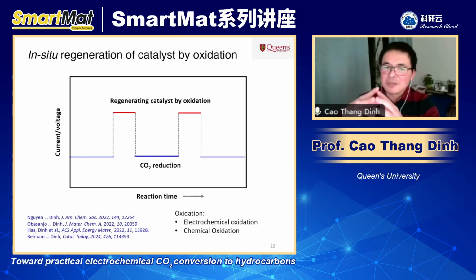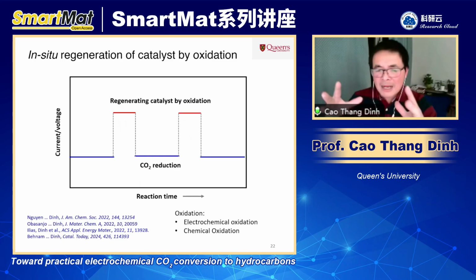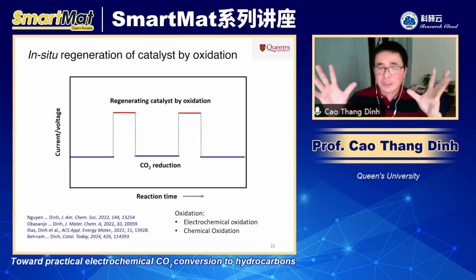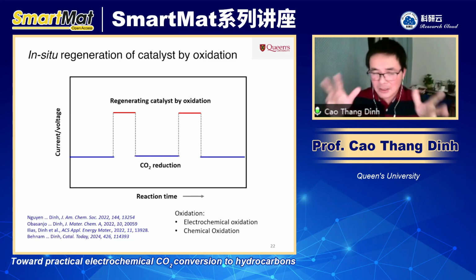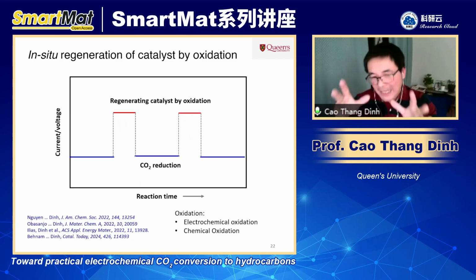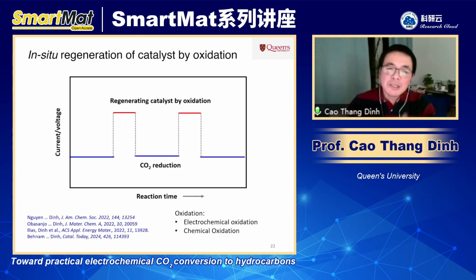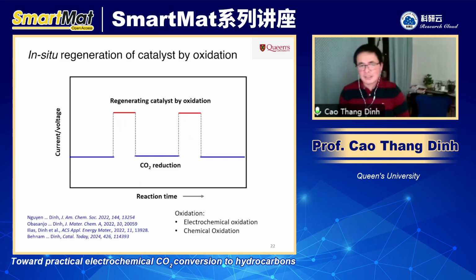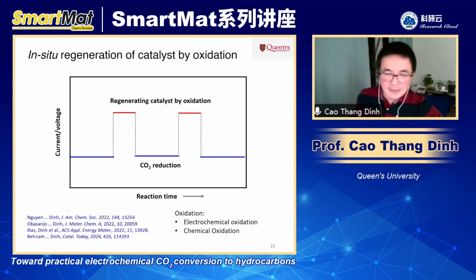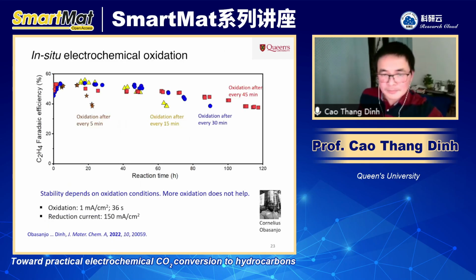And what you can do here is oxidize the surface either by electrochemical oxidation, which makes a lot of sense, right? You have an electrochemical cell, you can just apply positive current, or change the voltage, and then you can oxidize your catalyst surface. But you can also use chemical oxidation. You can introduce some oxidizing agent to your system so that you can oxidize the surface of the catalyst. So we apply different strategies for different metals, but I just want to show two examples here for copper catalyst. Okay, so the first one is that we just use simple oxidation, like applying positive current, right?